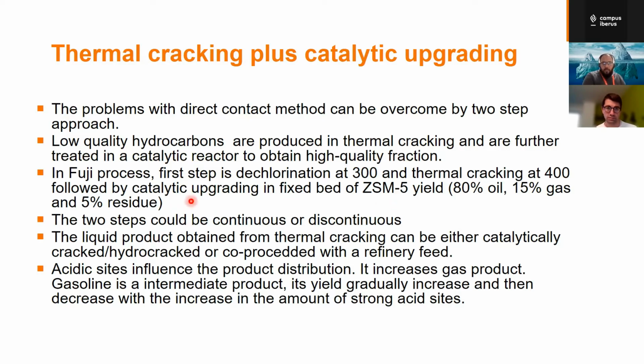This is one example of a Fuji process where dechlorination happens at 300 Celsius, because chlorine is volatile at this temperature. You get rid of the chlorine, you thermally crack it in one reactor at 400 Celsius, and then you catalytically upgrade the vapors in a different vessel containing zeolite catalyst. This approach can be continuous or discontinuous, and the liquid product that you get from the thermal cracking can be catalytically hydrocracked also using hydrogen.